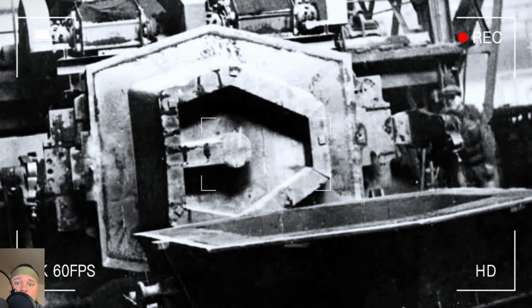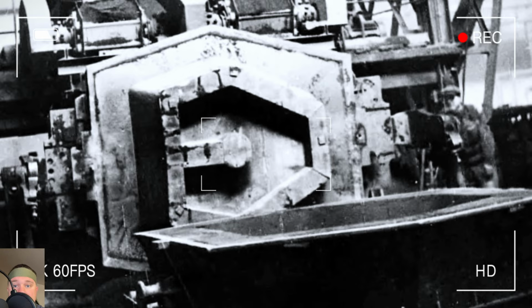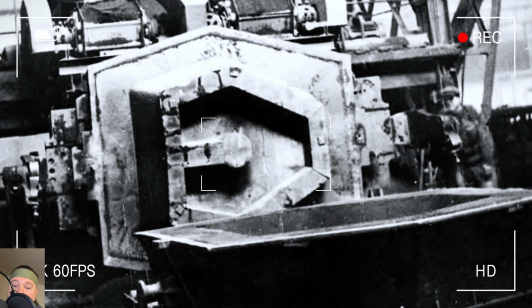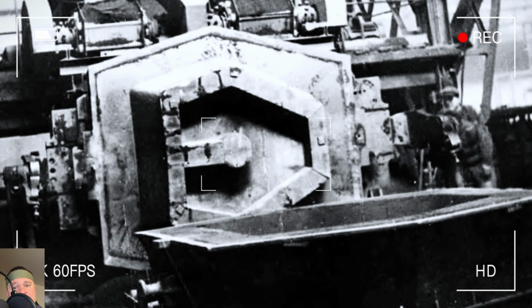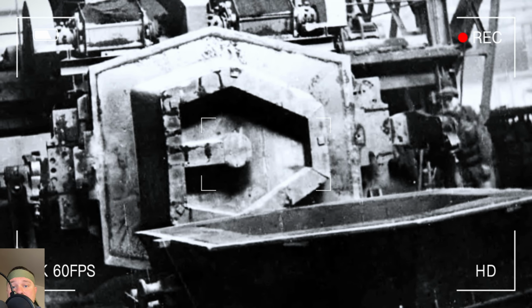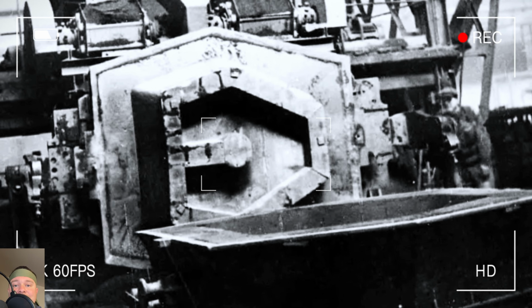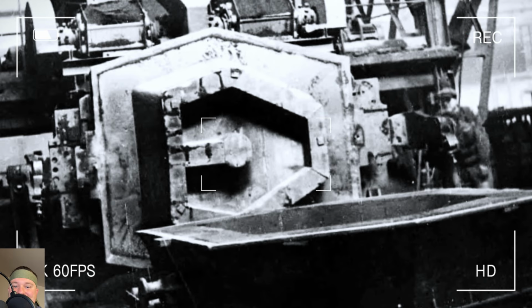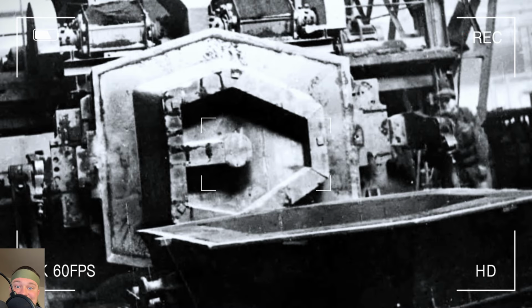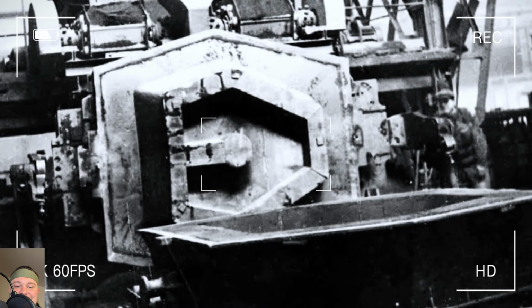This caused the metal in the cutting zone to heat up instantly and intensely, then cool just as rapidly. This created monstrous localized stress. This stress piled on top of the internal stress already in the turret from casting, which hadn't been fully relieved by tempering. But why did the cracks appear specifically under the feeder heads?